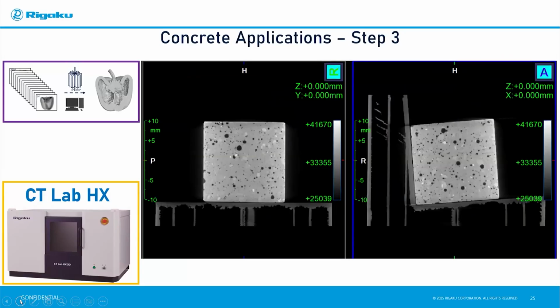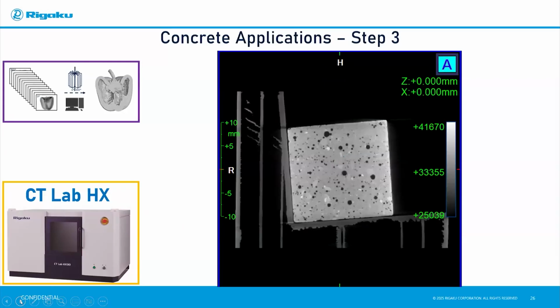The next slide demonstrates our sample with a zoom, and we can observe the concrete sample itself. It's a gray color, but we can also observe different white phases, sands, and different aggregates, which demonstrate the multi-component character of this sample. And of course, we observe different pores and bubbles, which reflect that this sample has a lot of air inside as well. It's another slide which demonstrates our sample with a good quality, everything is clean, and the image is sharp.